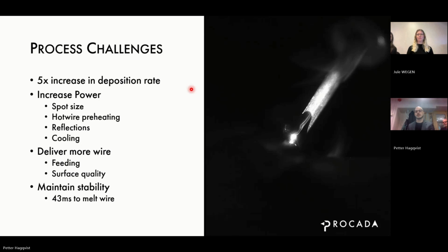So as I mentioned, the challenges here in the process is that we're making a 5-fold increase in deposition rate compared to the baseline we had prior to this project. In order to do this, we needed to increase the power, of course. There is more material to melt, so we need more power. We can't just increase the laser power without increasing the laser spot size, because then the power density will get too high and will just evaporate the material or a large portion of it. So we need to increase the spot size. And in this case, we had to stick with the optics we had. So we went with a specially purchased fiber which had a core diameter of 1500 microns, which is a very thick and very fragile fiber.